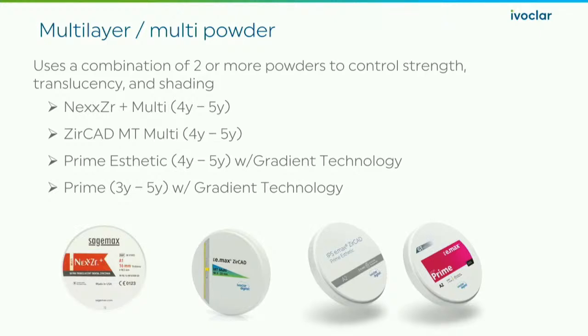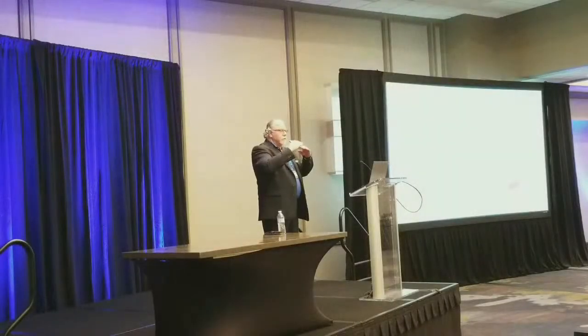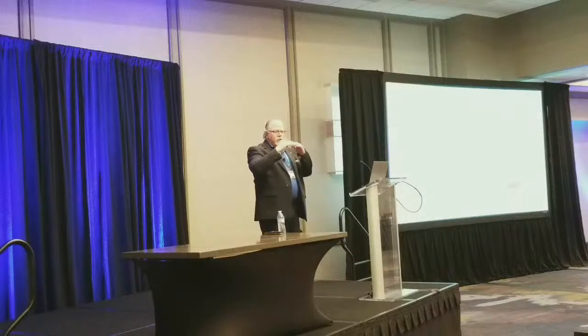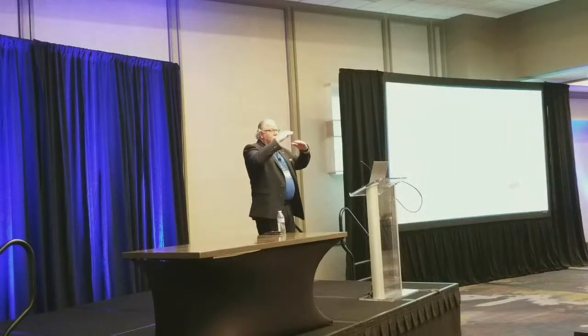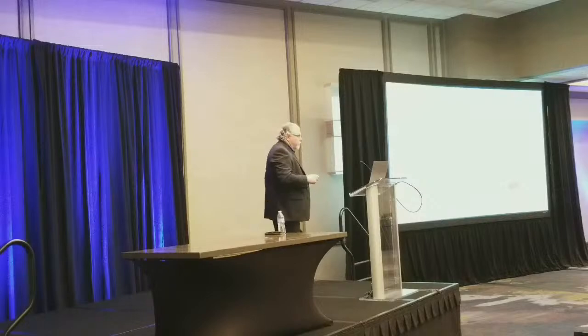The other ones, the 4Ys in the SageMax, in the MT Multi, those again are two different powders. They're a 4Y and a 5Y material. Of course, as we know as ceramists, when we're working with different materials, there are coefficient of thermal expansion differences. There are all these things that are going on. And of course, with a 4Y and a 5Y or a 3Y and a 5Y, there's a tremendous amount of things going on between those two if we just stack them on top of each other. So as they sinter, the sintering kinetics for each of those materials are different. So they cause stresses among themselves microscopically, but what you end up seeing is bridges rocking, perhaps cracks or delamination between the materials. You can see lines. Things like that happen in those materials.